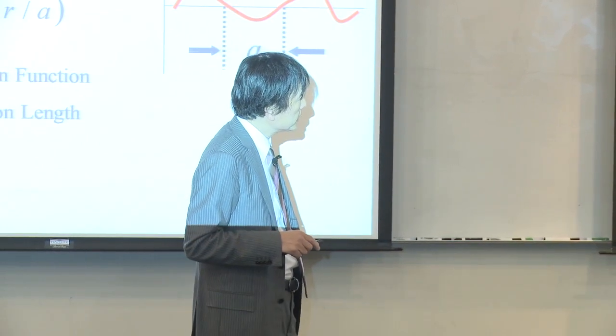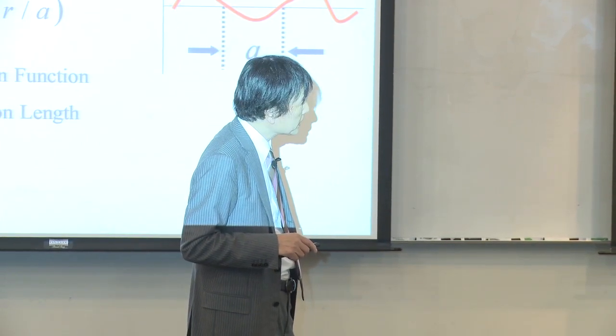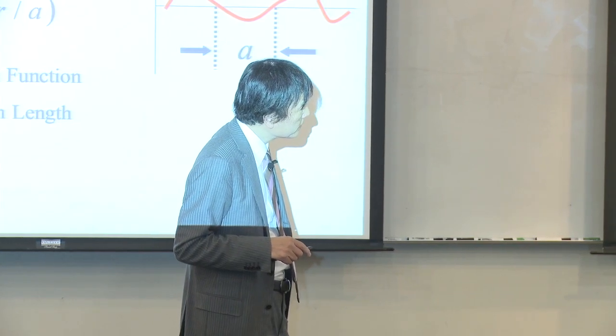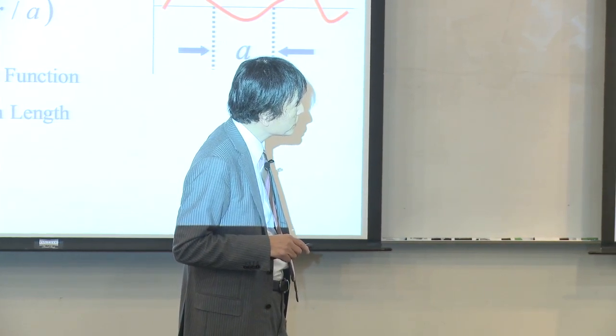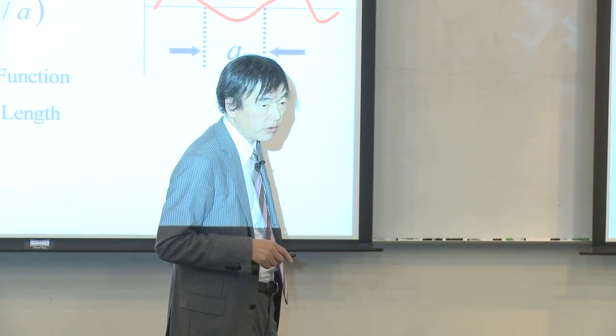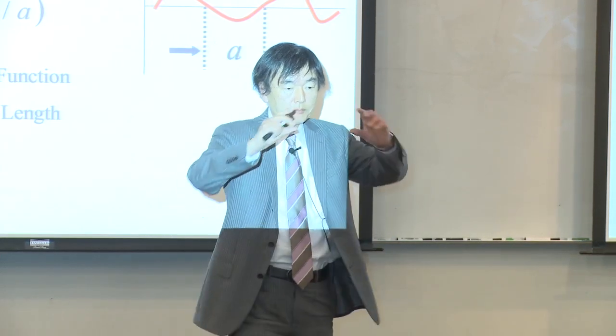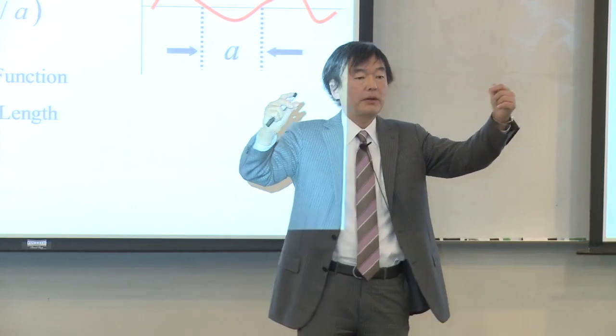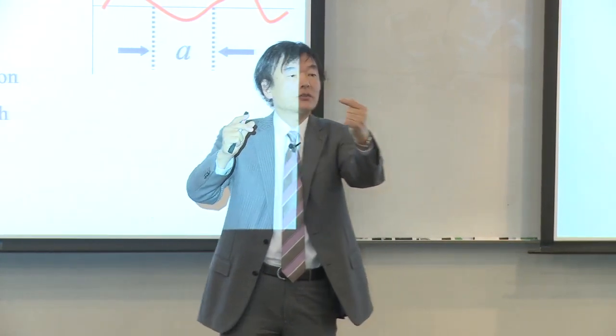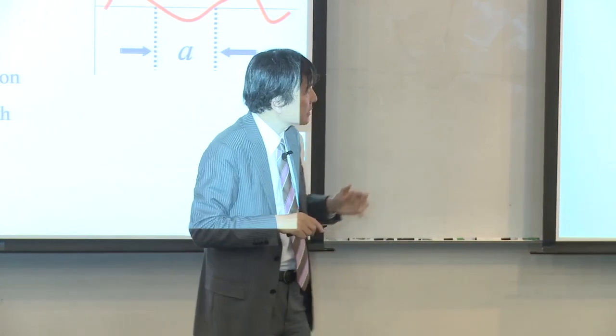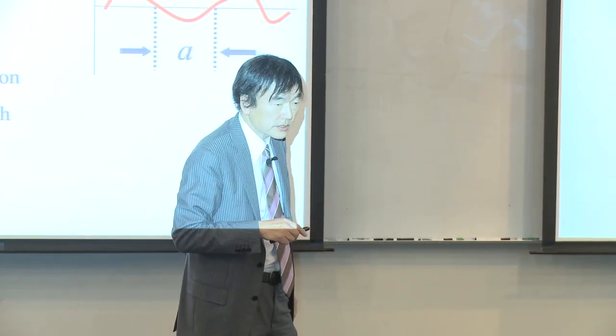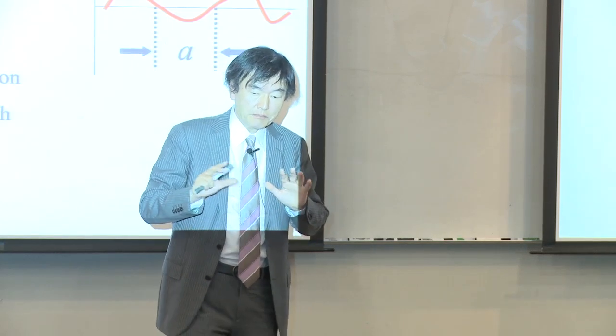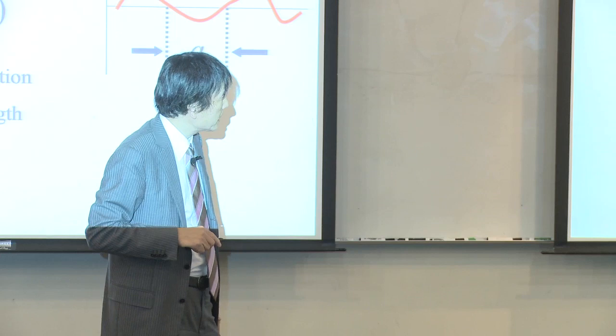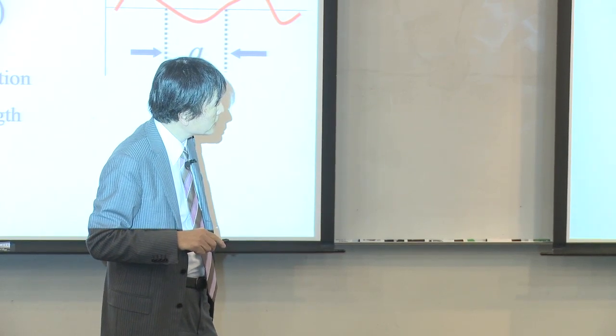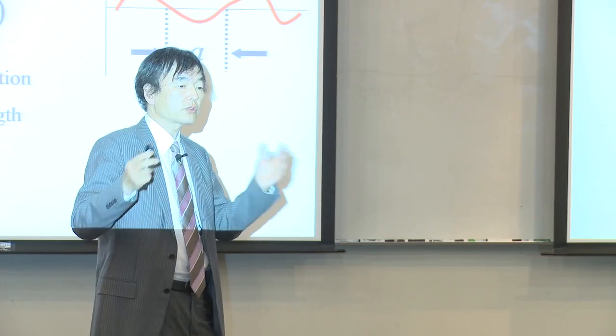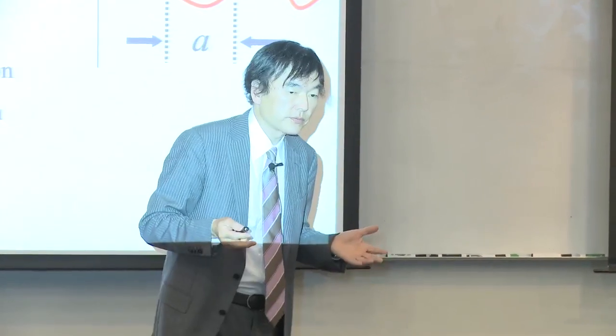Now, this is the transparent polymer, but the refractive index is slightly fluctuating like this. That has been overlooked so far because the polymer fiber looks transparent, but injecting the laser, you can certainly see the trajectories, so some heterogeneous structure exists. And the shape is really ambiguous, but the correlation length a is a measure of the size of the heterogeneity roughly, and also a measure of the shapes.